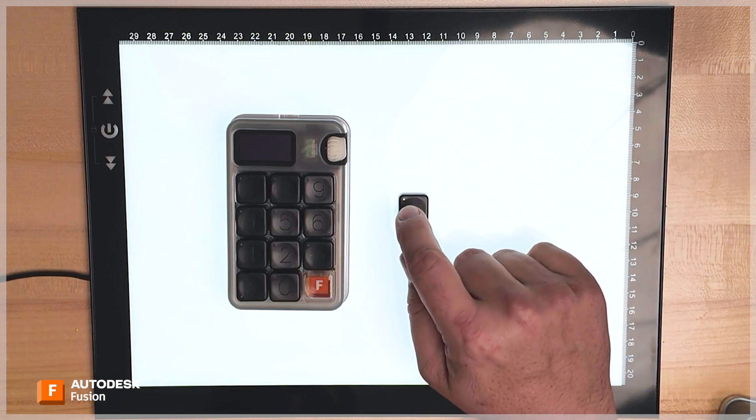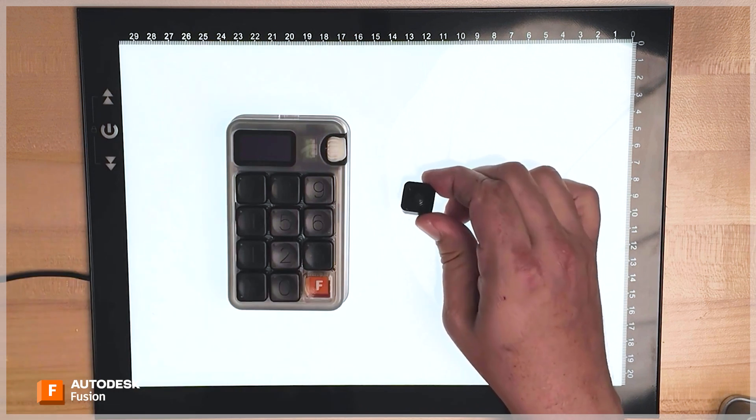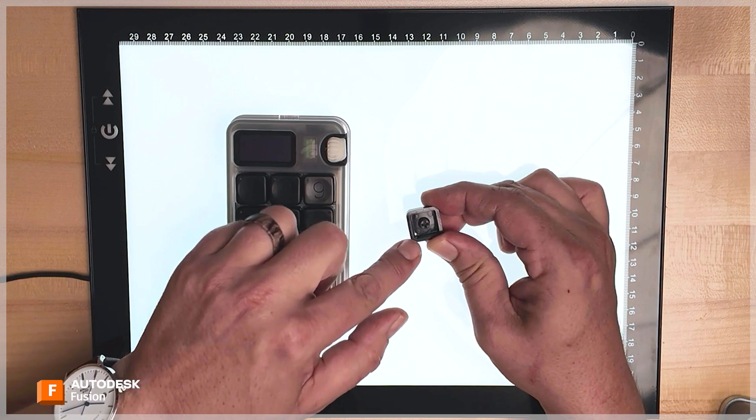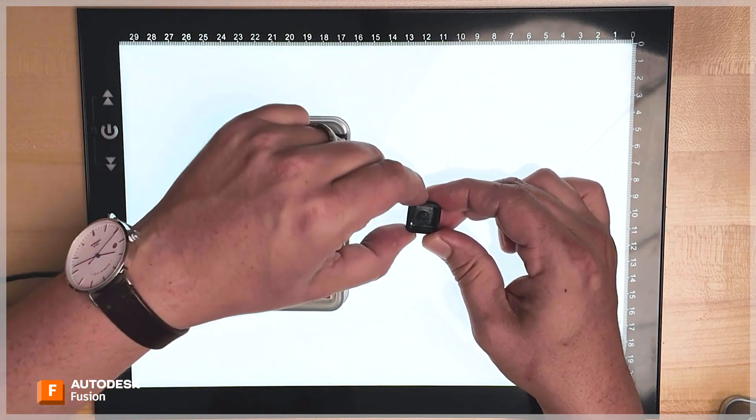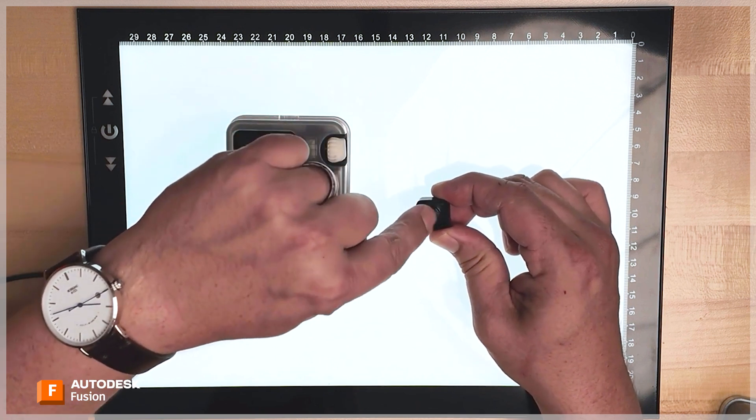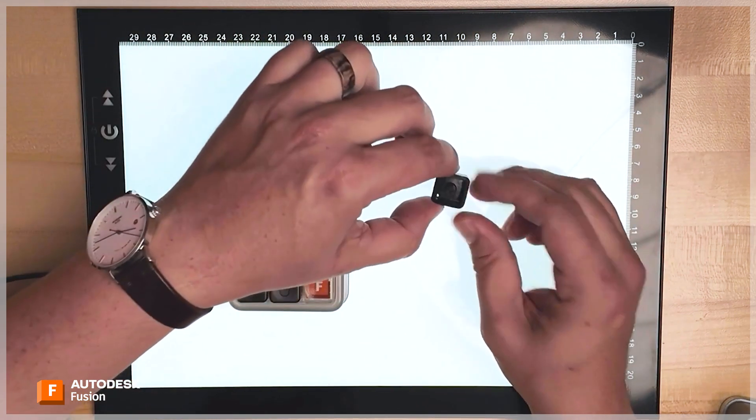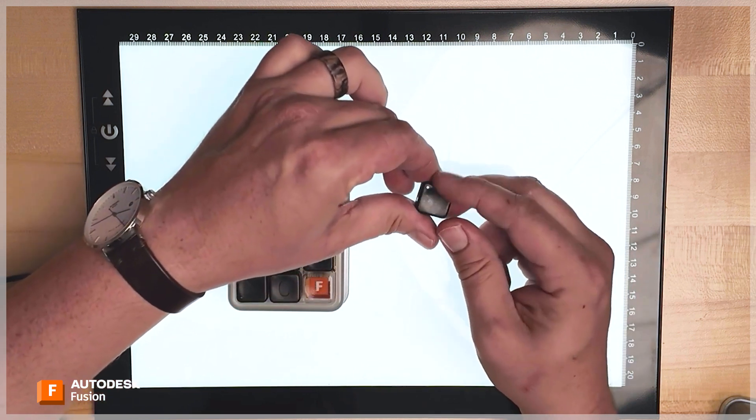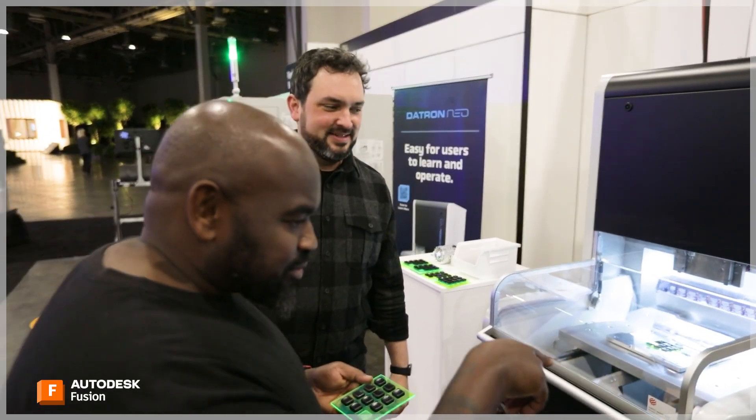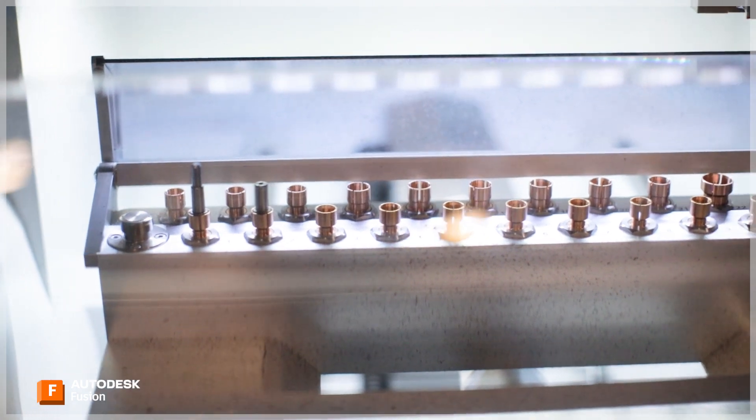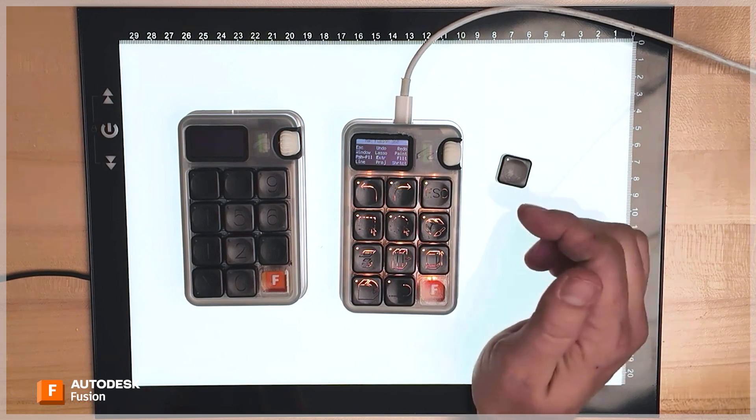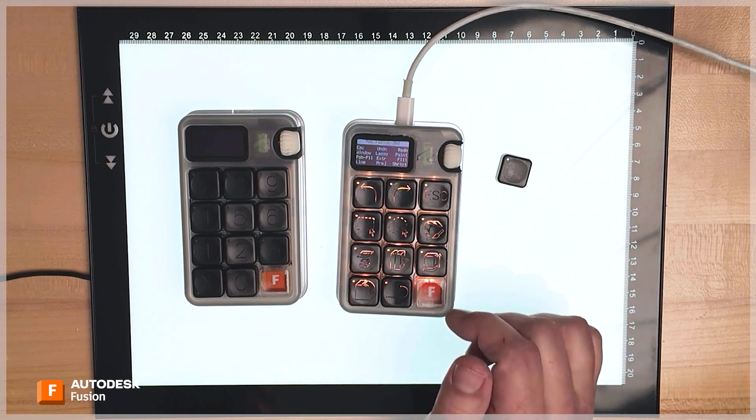Another cool thing about this product is the keys. So it's got key caps that have, if you look here, you'll see a little white dot right there. And that's my light table glowing through. So this is a two-shot injection mold. There's a clear core with a black shell around the outside. So you have a set of these. I think it was four or five in the mold. You do the clear injection molded part. And then they pop out and you stick that little piece where they're all stuck together into another mold. And then the black polycarbonate is injection molded around it on top of it, basically. So you have a solid monolithic object, but it's got this shell with two parts.